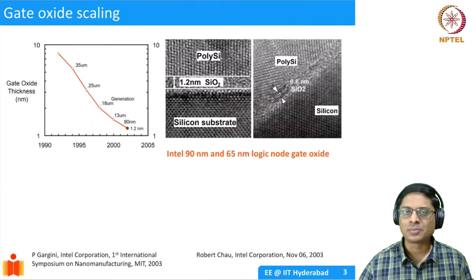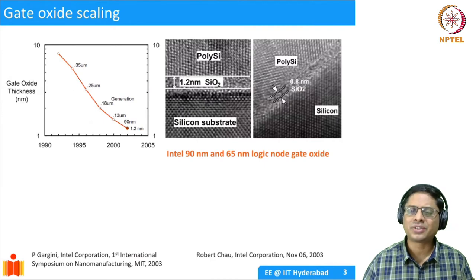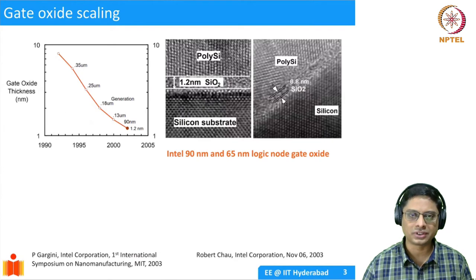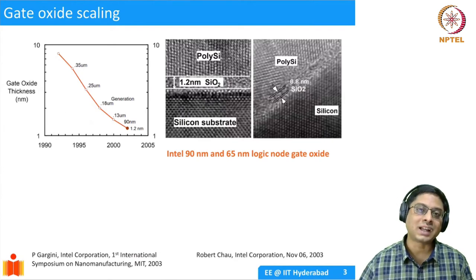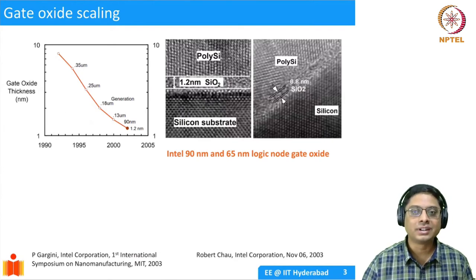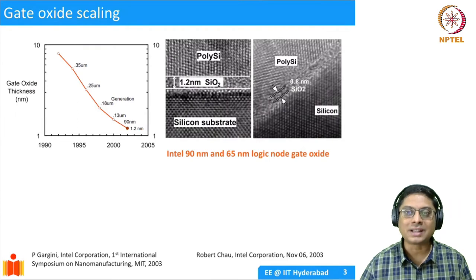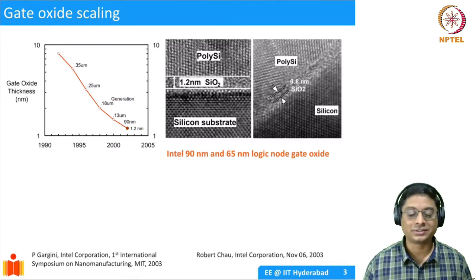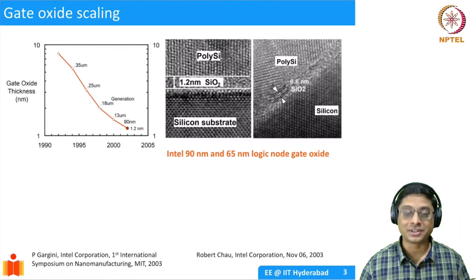Just imagine, 1.2 nanometers is maybe 5 to 6 atomic layers thick. Just 5 to 6 atomic layers. It's not microns. We mentioned that the thickness of a human hair is a few microns. 1,000 times smaller than that is 1 nanometer. And effectively, the capacitor we are building is with just 1.2 nanometers of silicon dioxide. This is magical, right? The fact that it actually worked is magical.